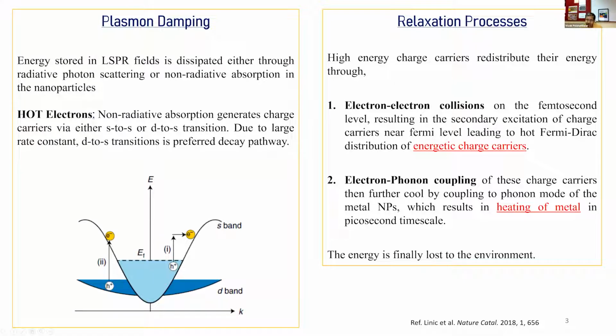If I cannot use these hot electrons, then the third phenomenon happens, which is that these electrons undergo electron-phonon coupling and lose all that energy in the form of heat, and you create localized heating of the surface. We call them thermal hotspots. And then one can use these thermal hotspots to carry out a thermal reaction. So you're using a photon to create isolated thermal energy directly on the catalytic surface, which will then allow us to carry out a thermal catalytic reaction.